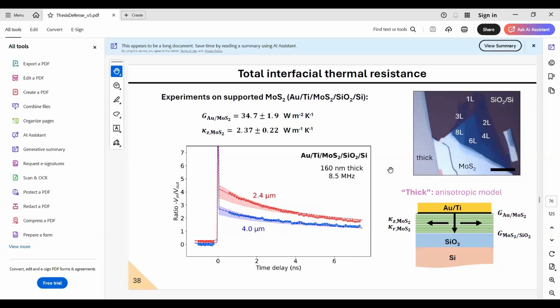Yeah, so related to this, and maybe you said this and I missed it, but did you quantify the G, the thermal boundary conductance, with the SiO2? We actually fixed it to the value you reported previously. Actually, we've tried to also extract it, but eventually you need to perform more measurements in more configurations to be able to extract all these unknown parameters. In this case, we are already extracting 2 parameters. Yeah, top interface and the thermal conductivity. And we are using 2 different spot sizes and 2 different modulation frequencies. So yes, we could have changed also the interfacial conductance, but we saw that we have way less sensitivity to the second interface compared to the first interface, and therefore fixed it to the value that people typically use, from 14 to 20. Then we use 18 watt per meter square Kelvin.